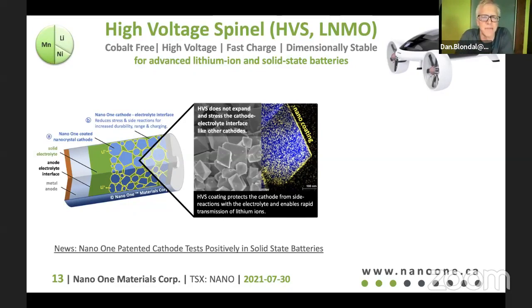So it tends to be a really low cost material. It doesn't have the cost of cobalt, doesn't have the extra cost of all the extra nickel. And you can see the crystal structures in the micrograph here are very different than the last one, very angular, octahedral looking structures. But again, we're able to apply this very thin nanometer layer skin on the outside of the particle. Now, I should say we kind of do this from the inside out. And this is what makes our coating technology very different.